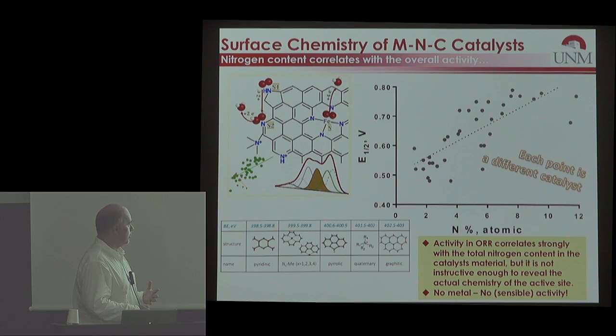But most of all, what is important is that this paper establishes the fact that there is more than one active site in each and every one of these catalysts. So we do not have a system with a single active site. We have a pluri-catalytic system. And I found the word multitudinous active sites, which is actually a GRE word. I didn't know it. I need to look at that in the dictionary.